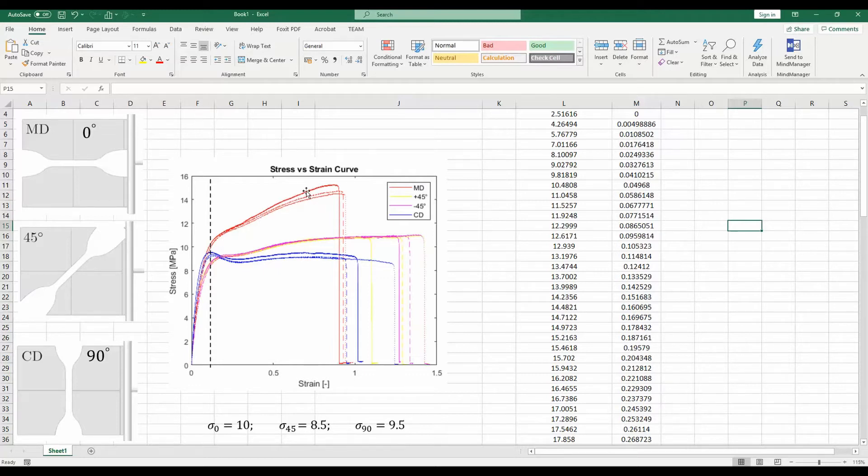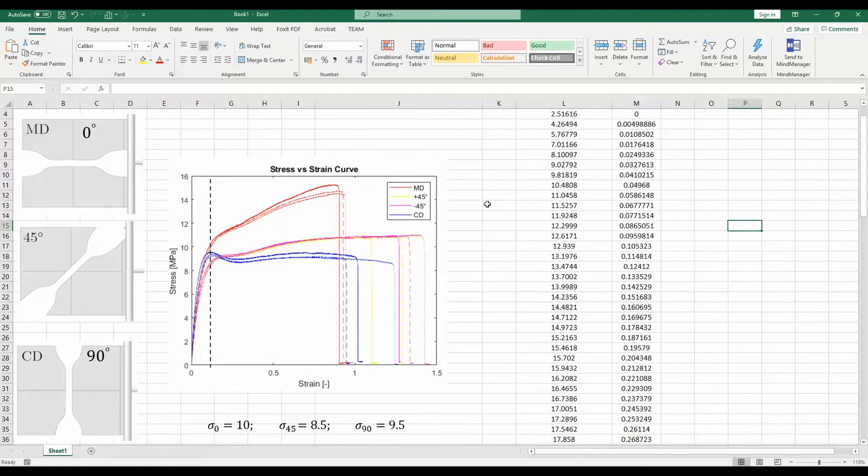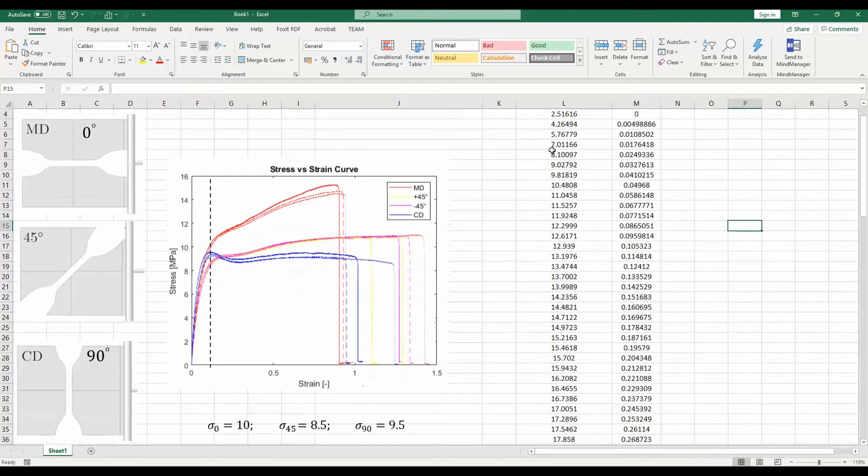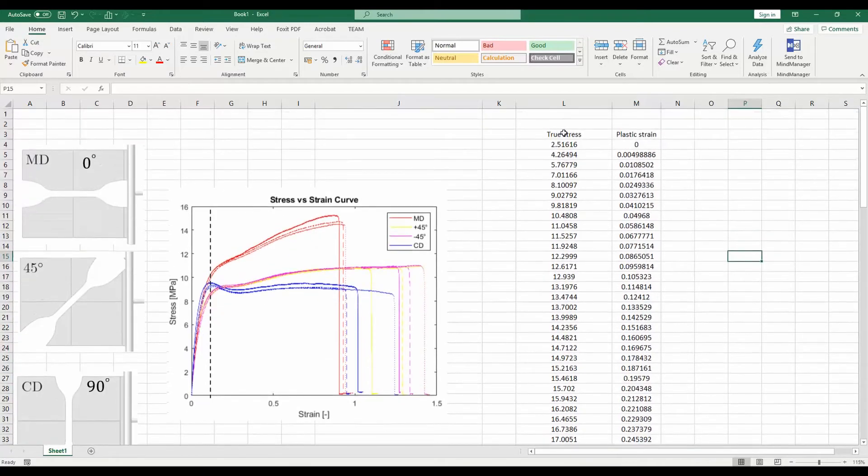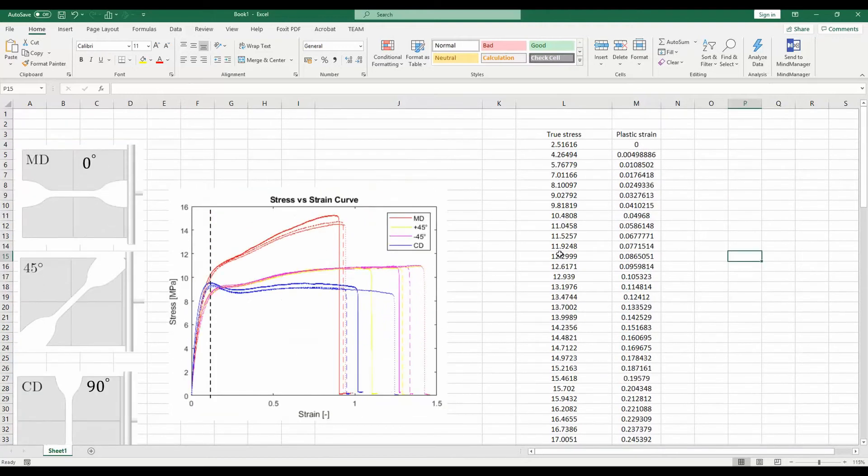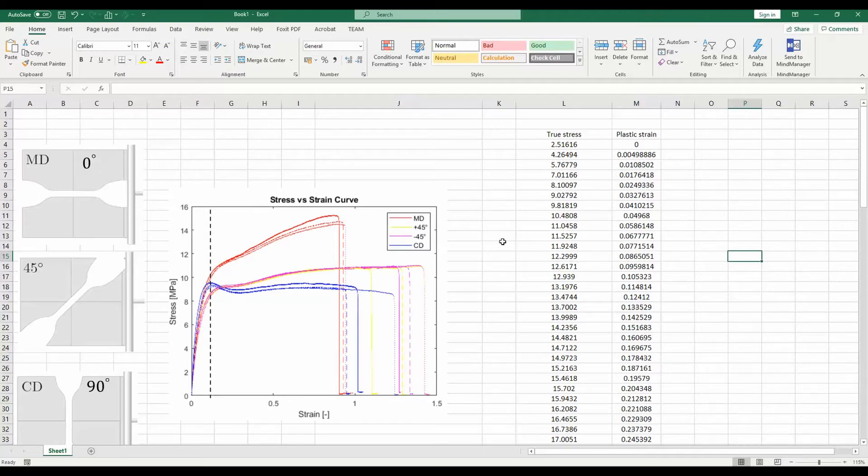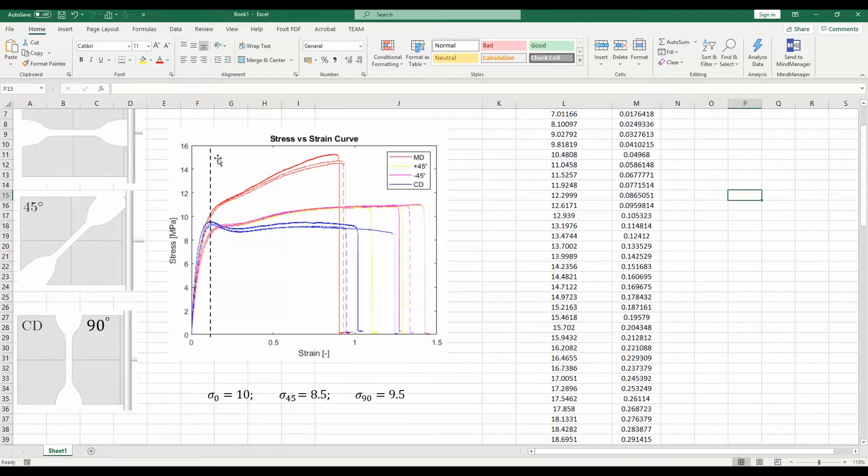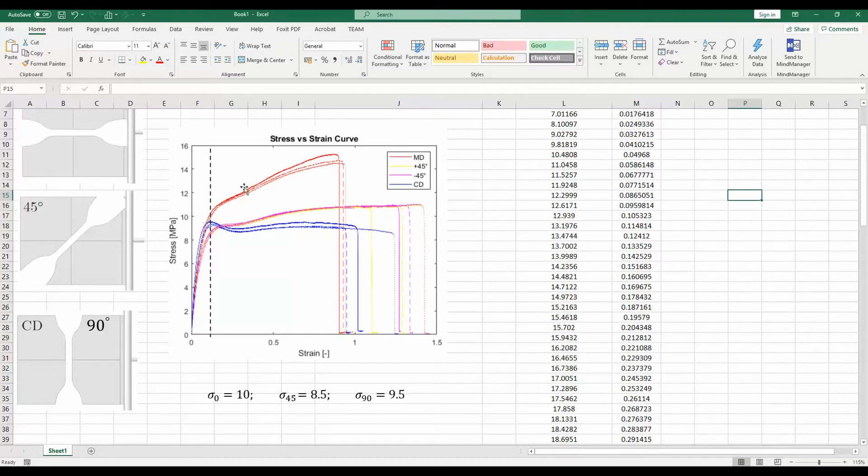You will pick one of the characteristic examples. If you do only one test, then just take that one and convert that stress-strain into true stress and plastic strain. This curve, in terms of true stress and plastic strain, will be our first input for the Hill anisotropic criterion. The next thing you have to do is find where this material starts to yield. For example, if we say that all these 0,